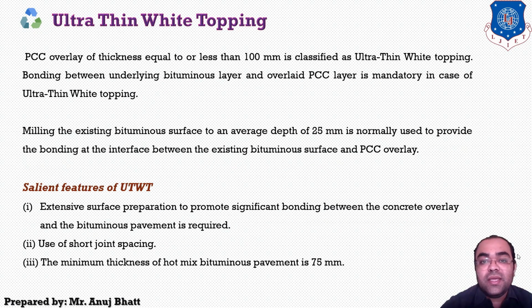Well, a PCC overlay of thickness equal to or less than 100 mm is classified as ultra thin white topping. Bonding between the underlying bituminous layer and the overlaid PCC layer is mandatory in case of ultra thin white topping. Milling the existing bituminous surface to an average depth of 25 mm is normally used to provide the bonding at the interface between the existing bituminous surface and the PCC overlay.